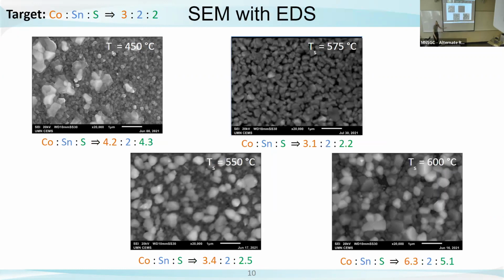And so we took these images and we did EDS on them, which is energy dispersive spectroscopy, in order to find out if the material within the film was actually what we wanted it to be. So our target was 3 to 2 to 2. And so we set our tin to 2 and then created our ratios from there. And you can see in the 450 that we're slightly higher with the other two values than we would like to be. And so as we increased temperature, shoot, the bar is in the way, but this one is 3.4 to 2 to 2.5. So getting closer to the ratio that we want.